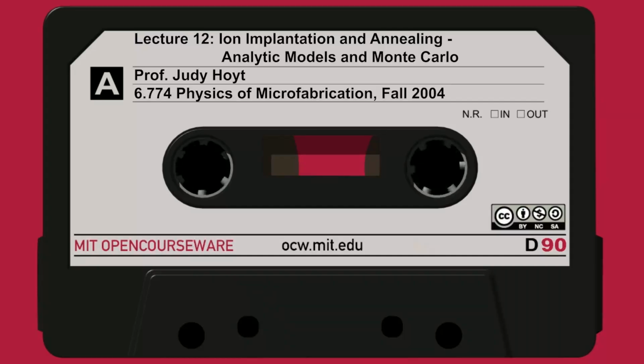Boron is the lightest of all those elements. So it kind of makes sense. Boron is lighter. It's going to lose less energy in its collisions. So it's going to travel further overall. And not only does it travel further into the crystal, its projected range here is about 0.5 or 0.55. It's also broader. Its distribution is very broad. Look how broad this is compared to the antimony, which has a very, very tight distribution. So as a physical process, it depends very much on the mass.